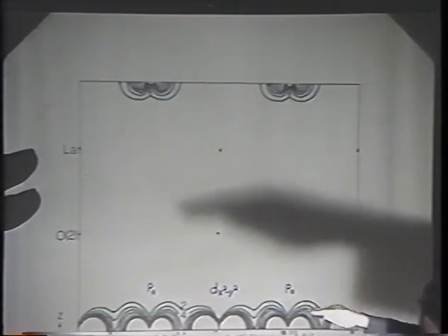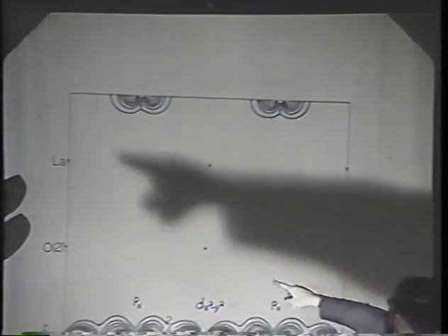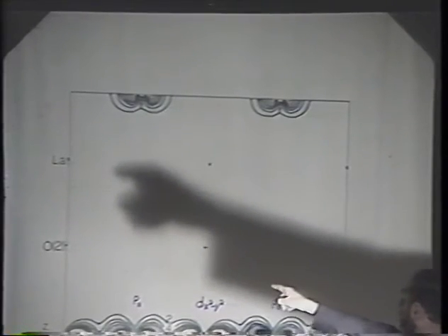If you look at the charge density, here is a vertical plane. Here's a state at the Fermi energy. Here are the copper-oxygen planes. You see the dx squared minus y squared orbital that Muller talked about, bonding with the p parallel. Notice no charge density in these states, in this region in between the planes. What you have is metallic sheets on the copper-oxygen planes. You have an insulator in between. The lanthanum shows no charge density distribution at all, so if you put a rare earth, there's no way the rare earth can really interact and with pair-breaking effects.